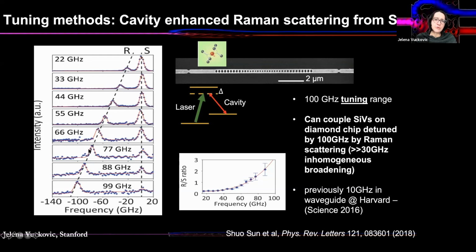But we've shown that by doing this, we can tune the scattered photon by up to 100 gigahertz, which is much more than inhomogeneous broadening of 30 gigahertz, meaning that by driving these quantum emitters with different lasers, you can basically interface them onto each other on the same chip.